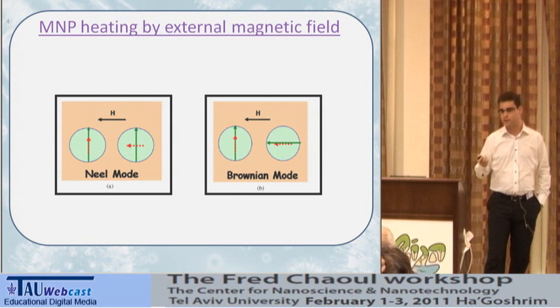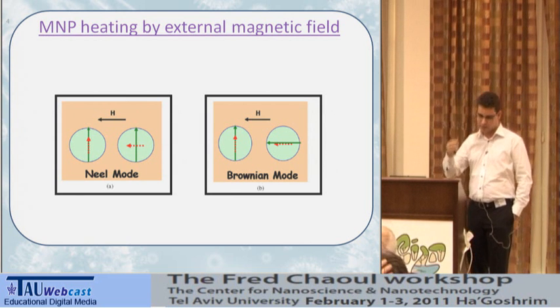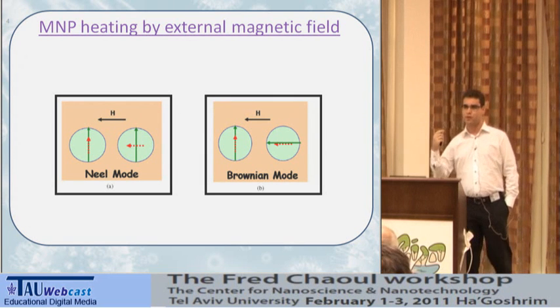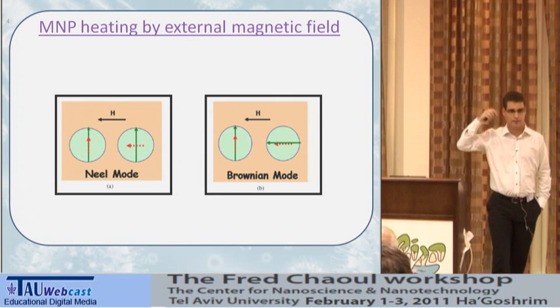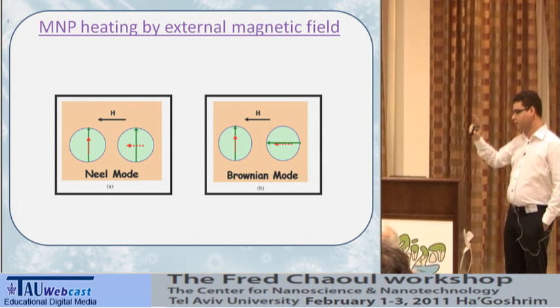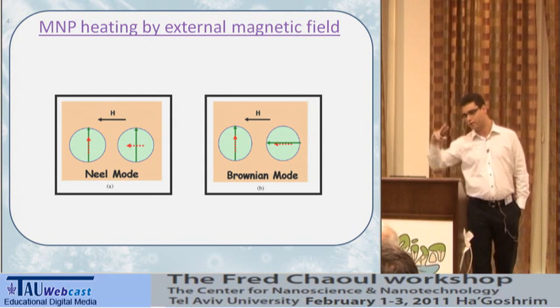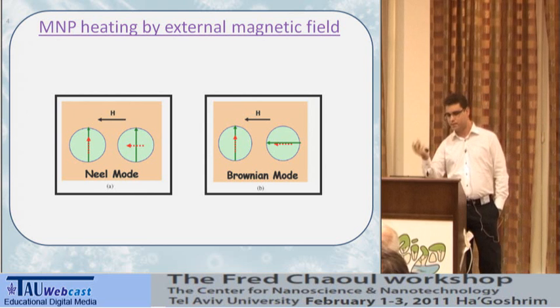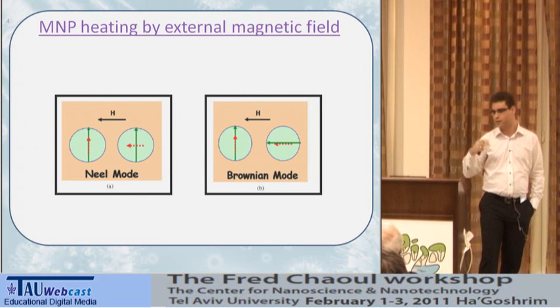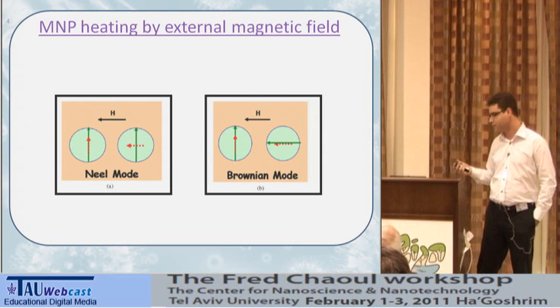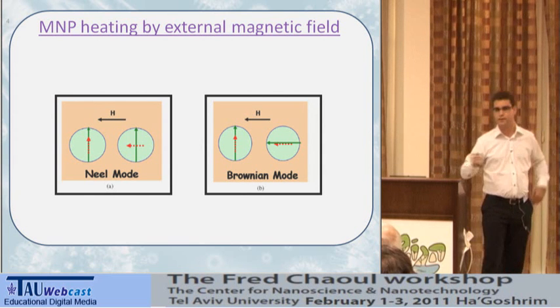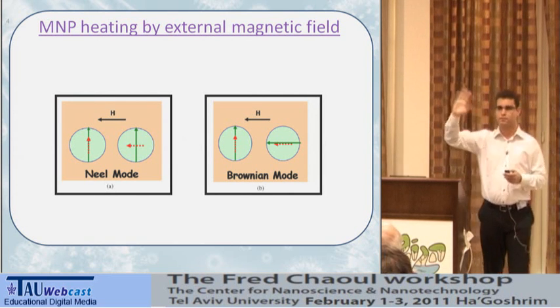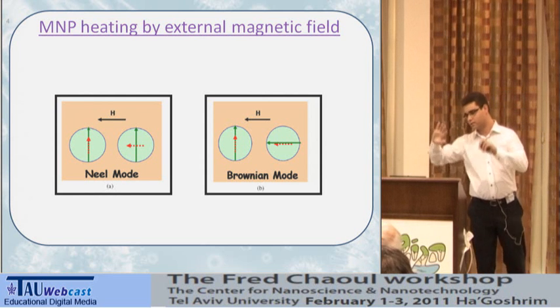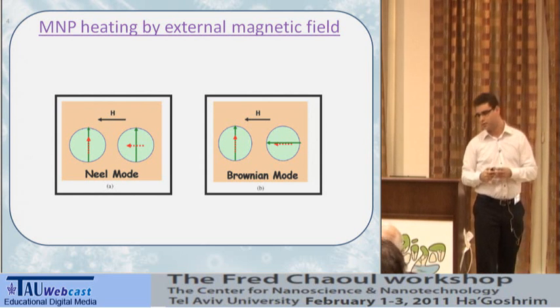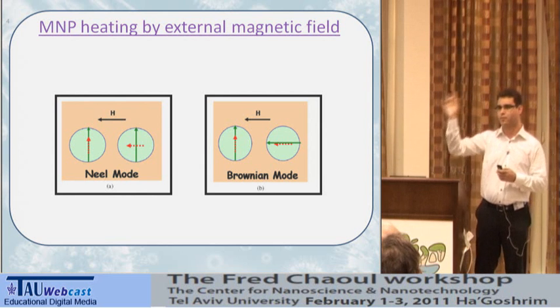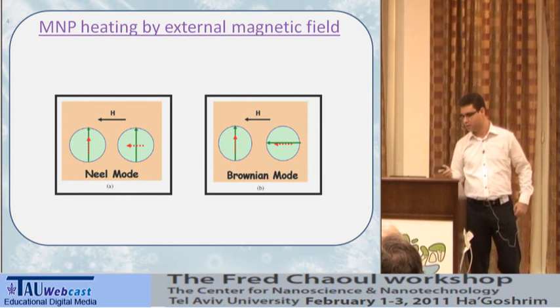One nice thing about these nanoparticles is that we can remotely deliver heat to them. If we apply an external oscillating magnetic field, we make these particles oscillate together with the external field, and they dissipate heat by two mechanisms. It's the Brownian relaxation and Néel relaxation. The Brownian relaxation means that the entire particle just rotates with the external field, thus generates heat, and the Néel mode is the same, but only the magnetic moment of the particle moves.